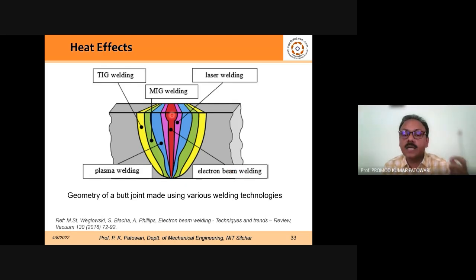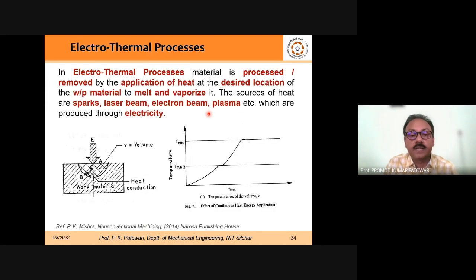So if you do the welding by laser and electron beam, you'll find that the heat is not being dissipated too much in the nearby area, because of the nature of the way you are applying the energy. It is because of the shorter pulses and high intensity, so that it remains within the confined area, but it can reach up to the depth. So ultimately you can say the penetration is more than the dissipation in the nearby area. So you want high penetration, and in a very short duration the entire process needs to be over, and the nearby area should not get affected. That is the philosophy that you should use, so that you can get a very effective and clean welding.